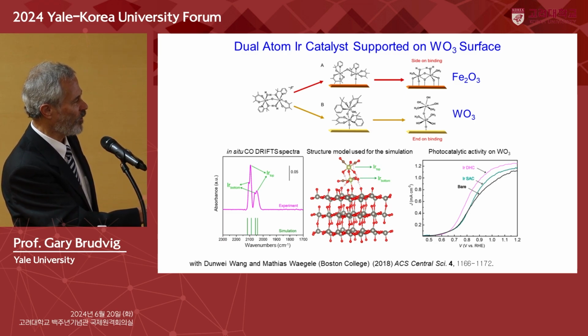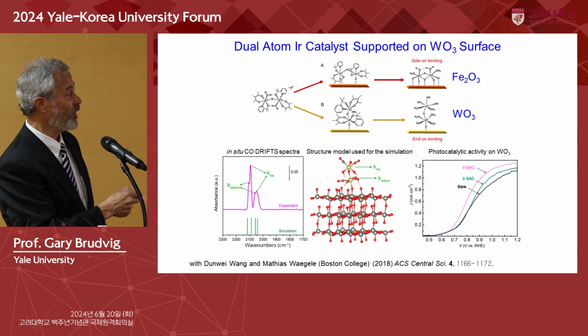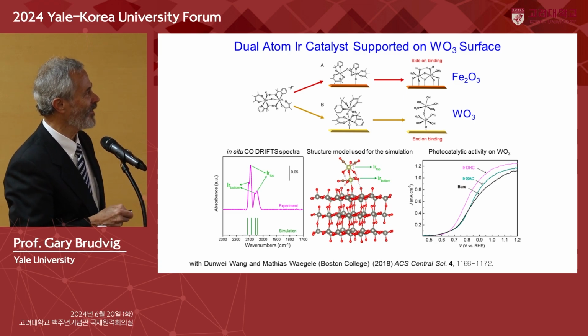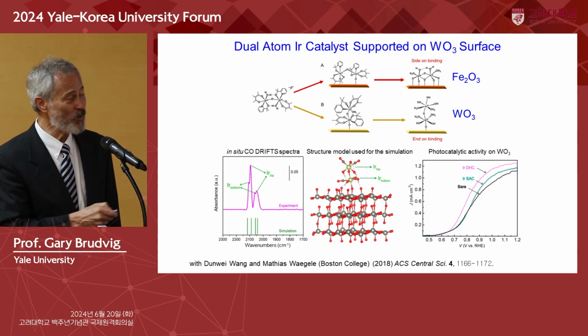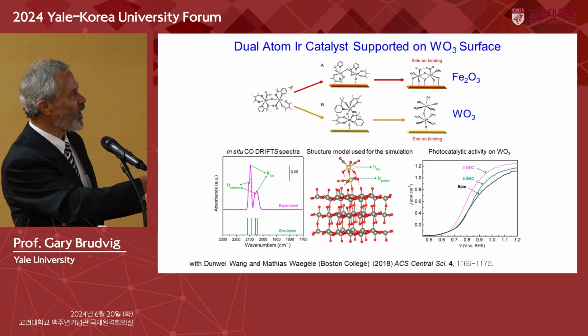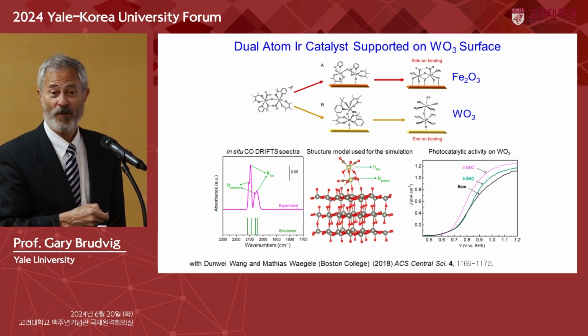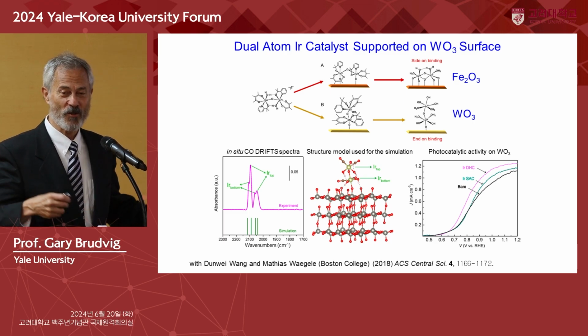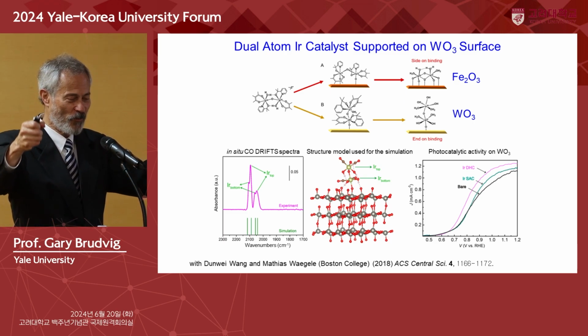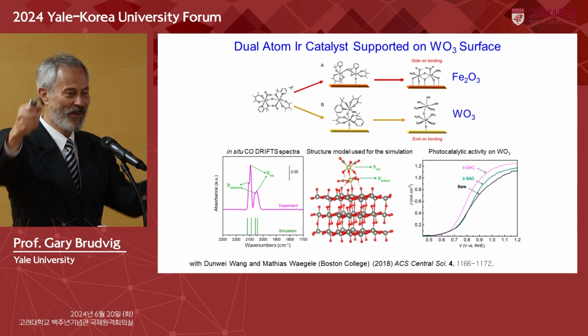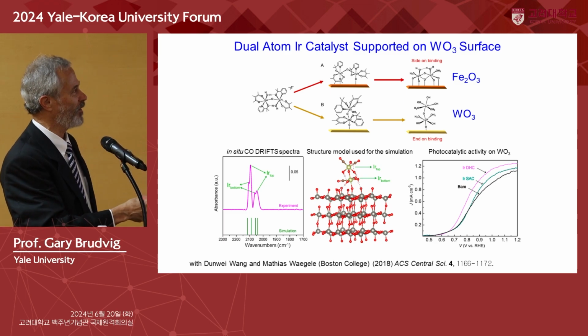And that's well agreeing with simulations. And so we modeled this as an end-on binding mode. And again, it's improving the catalysis. So this is interesting. And we think the reason that it's binding end-on is that the lattice spacing of tungsten is larger than the lattice spacing of iron oxide. So the sites are too far apart to lay down side-on. So that forces them to lay down end-on.